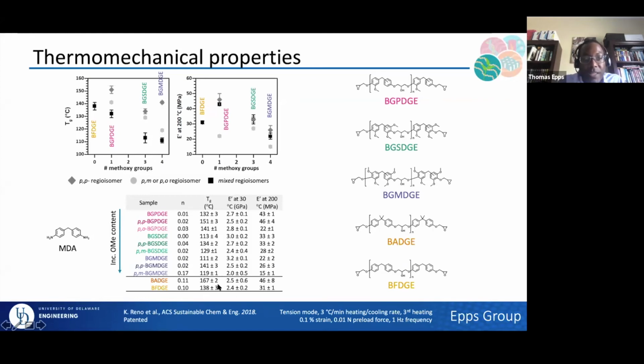So we get similar glass transition temperatures. We get similar moduli, both at 30 degrees, where we want a relatively high modulus. You can see they're all on the order of 2.5 to 3 gigapascals for both the commercial materials as well as our systems, as well as a little bit softer material that's easier to process at 200 degrees, where you can see now we're in about the 20 to 40 megapascal range.